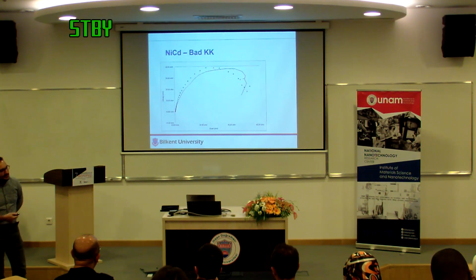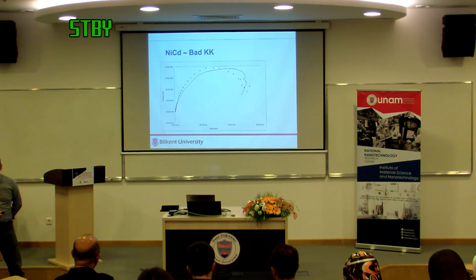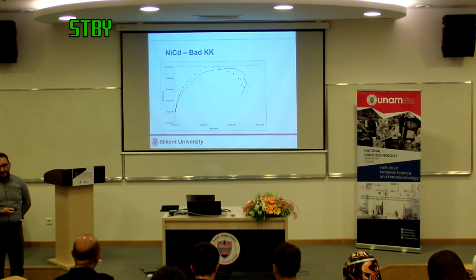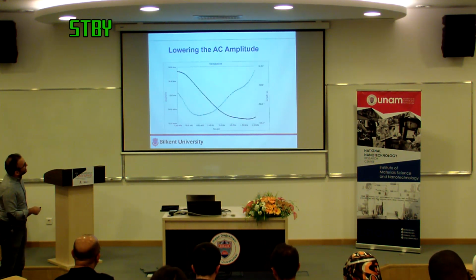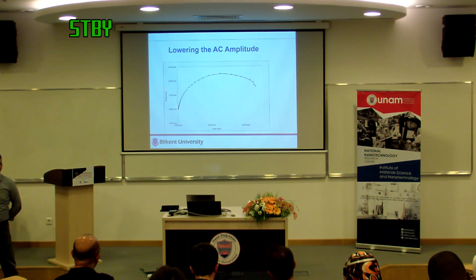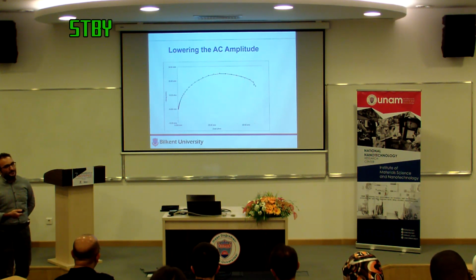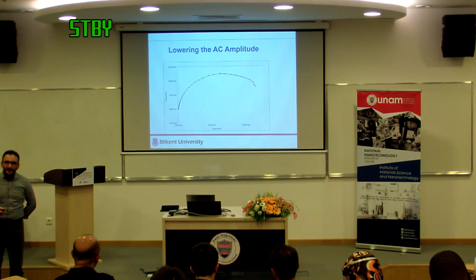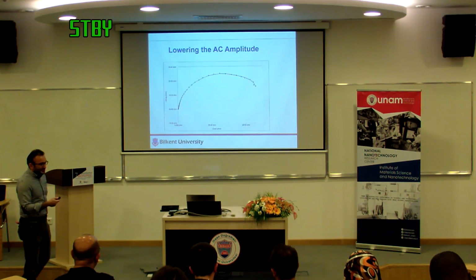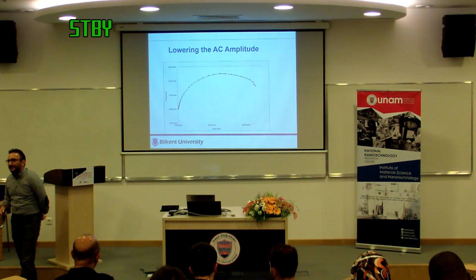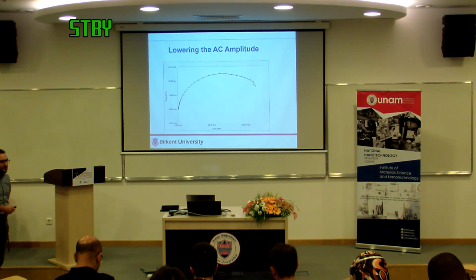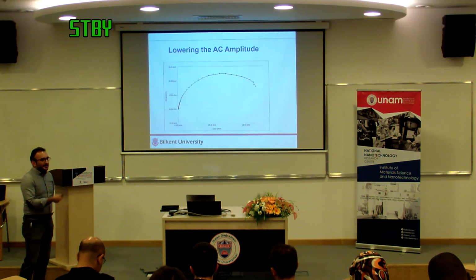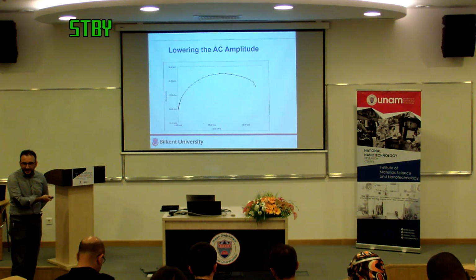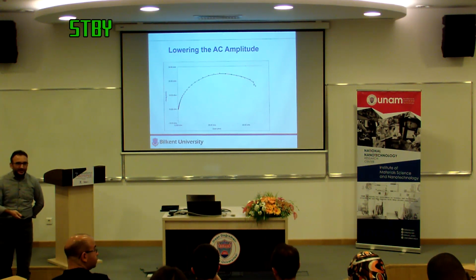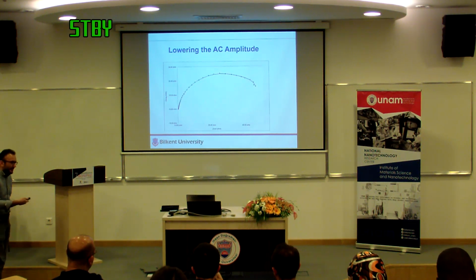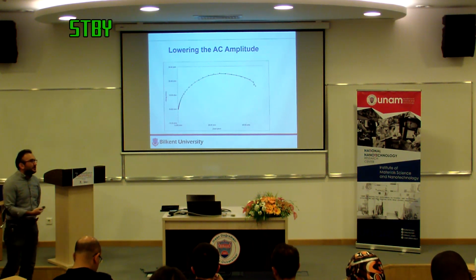How do I check it? Well, this was done with 1 millivolt AC amplitude. So I said, all right, the next experiment is to go to lower AC amplitude. And going to 0.1 millivolt worked. So the previous data was nonlinear because the amplitude was too high for this particular sample. Now in the impedance spectroscopy textbooks or beginner literature, you will always see people say 10 millivolts is the magic amplitude to use, and it never is. Here 1 millivolt was too much and 0.1 was the right amplitude. I've seen samples where 1 volt is good enough. So you have to get your sample to tell you what amplitude you need to use.